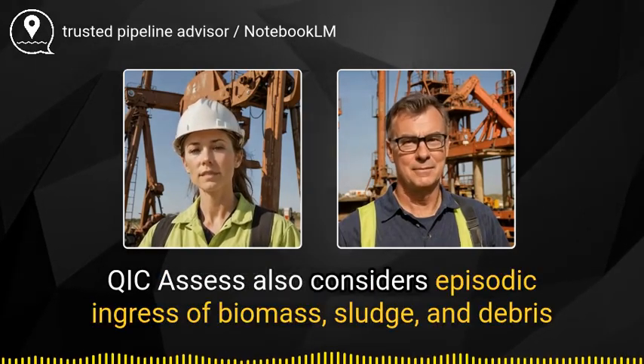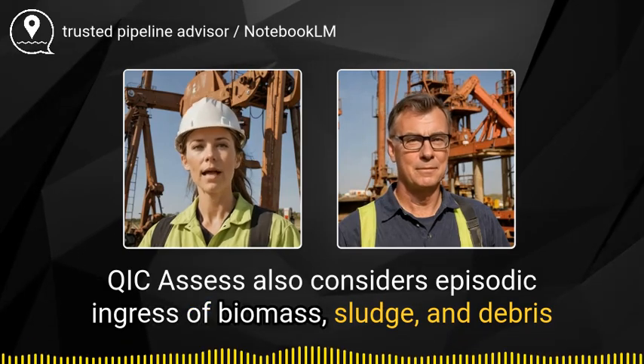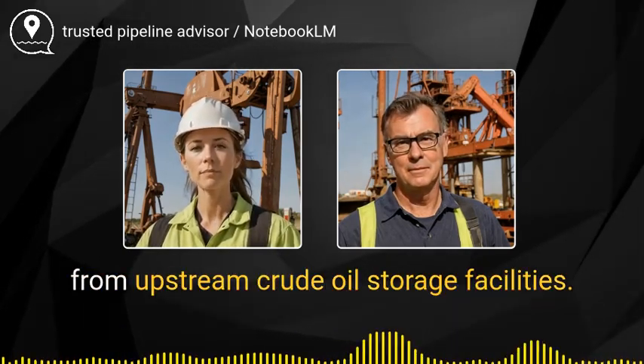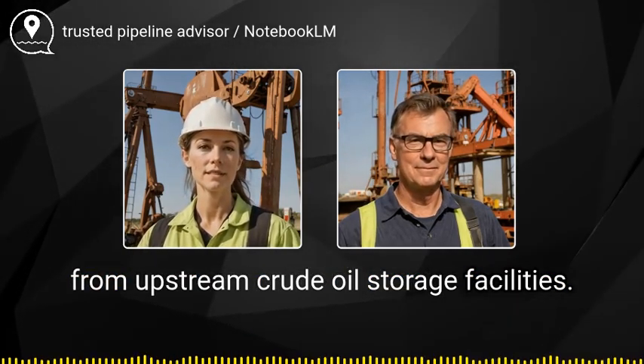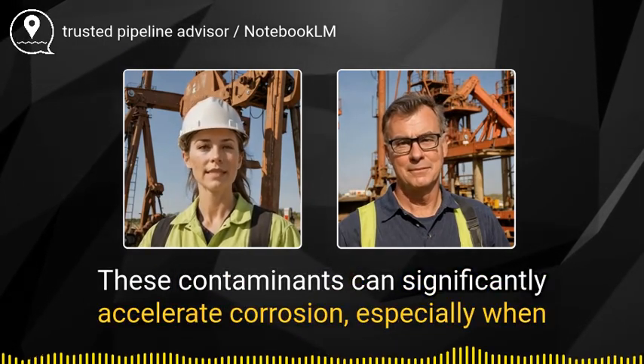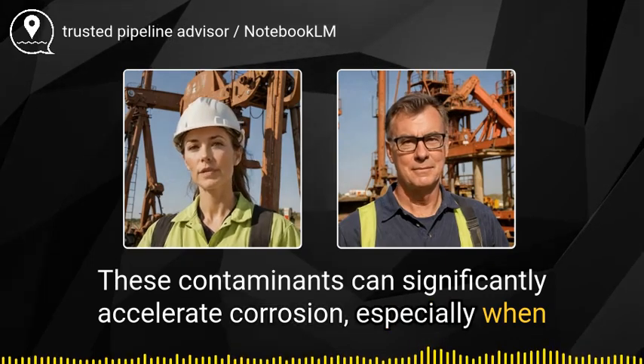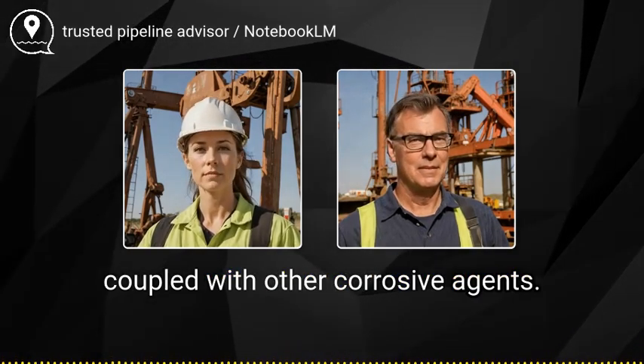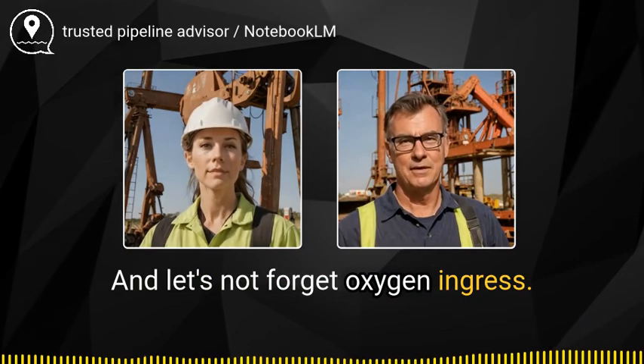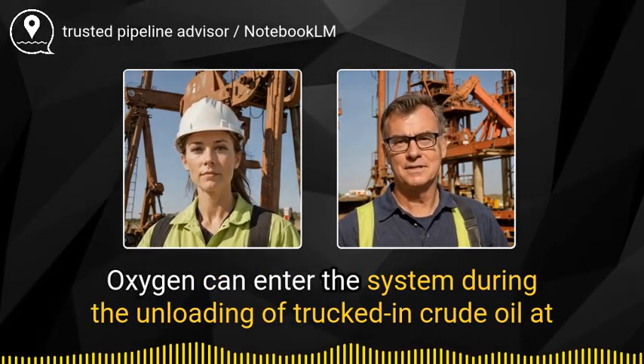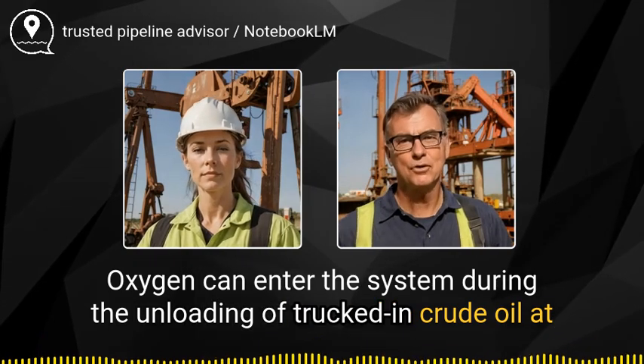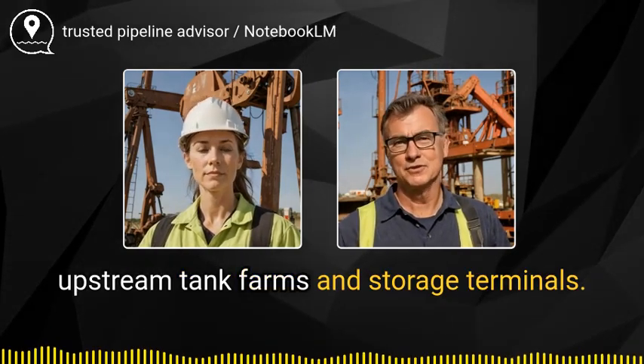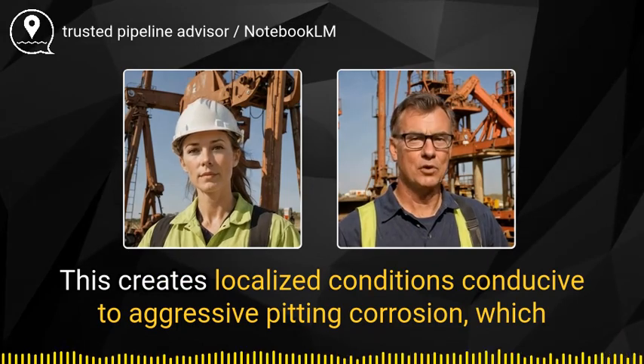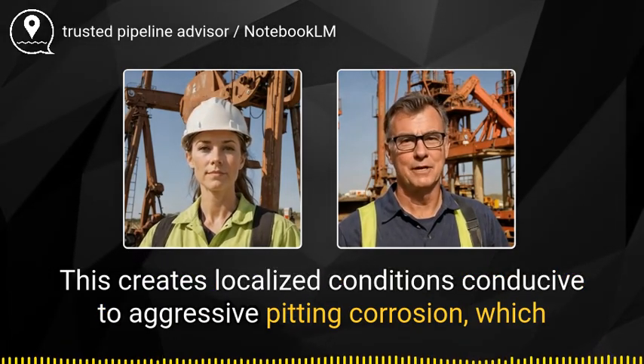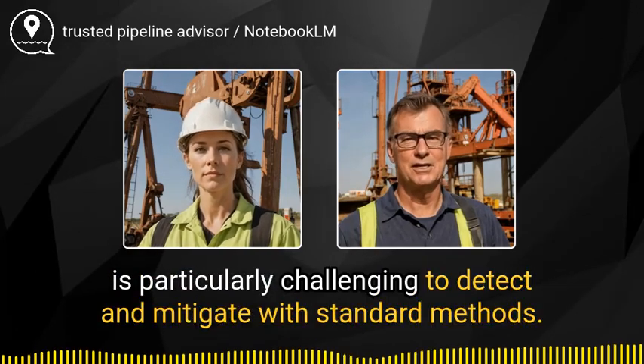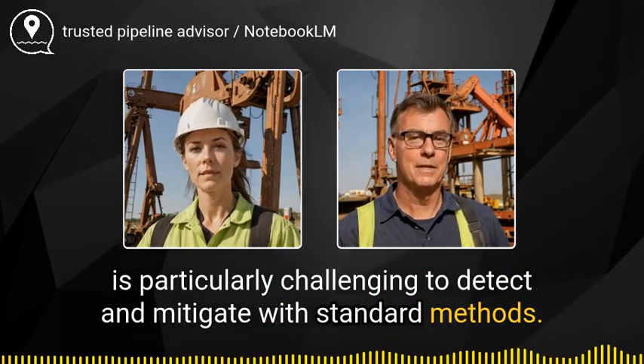QIC Assess also considers episodic ingress of biomass, sludge, and debris from upstream crude oil storage facilities. These contaminants can significantly accelerate corrosion, especially when coupled with other corrosive agents. And let's not forget oxygen ingress. Oxygen can enter the system during the unloading of trucked-in crude oil at upstream tank farms and storage terminals. This creates localized conditions conducive to aggressive pitting corrosion, which is particularly challenging to detect and mitigate with standard methods.